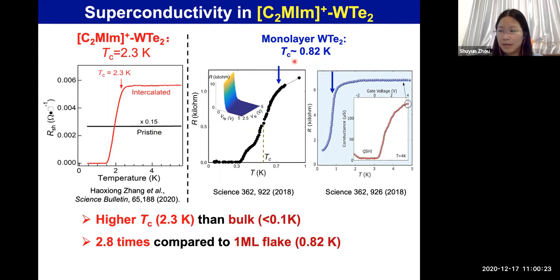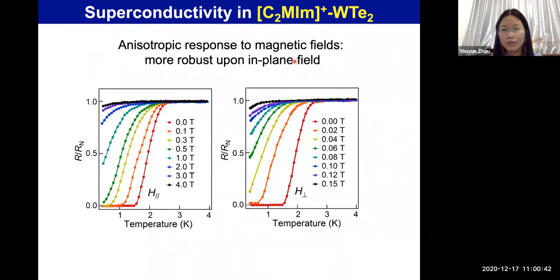So this tells us that this intercalation method not only gives properties similar to the monolayer flake, but sometimes we can achieve properties even better than the monolayer flake. And we find that the superconductivity in this intercalated tungsten ditelluride also shows a very anisotropic response to applied magnetic field. It's much less sensitive to the in-plane magnetic field, and much more sensitive to the out-of-plane magnetic field, suggesting that the superconductivity is also highly two-dimensional.